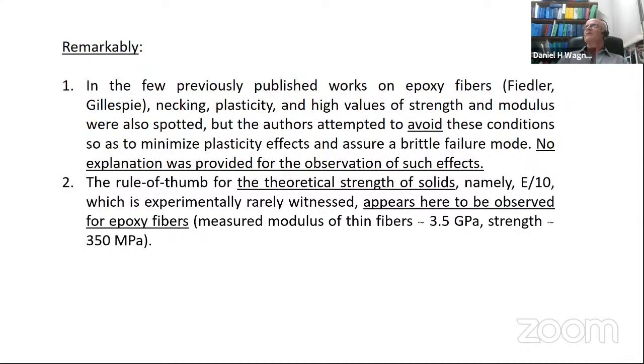There is another really amazing observation, both for our data and the previous data: usually materials never reach their theoretical strengths. Maybe carbon nanotubes or diamond, or single crystals, but for most materials, you never reach the theoretical strength of solids. What is the theoretical strength of a solid? There is a rule of thumb: take the Young's modulus, divide by 10, and you get the theoretical strength. It's really not witnessed, or rarely witnessed. And here it works. It's observed for epoxy fibers because the modulus is on the order of 3.5 gigapascal and the strength is 350 megapascal. So you have exactly E divided by 10, which is really impressive.